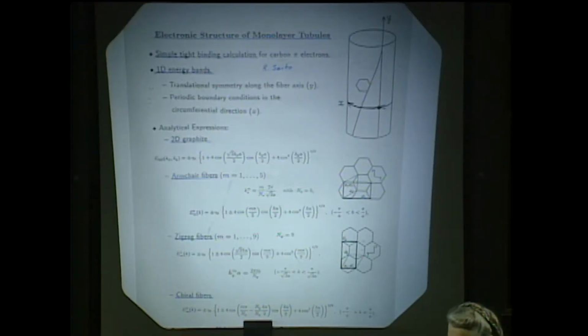The argument is based on the following concept, that when we have the tube, we make the tube like this, and we have a finite number of carbon atoms that go around the circumference. The number of wave vectors that we would have assigned to the system in reciprocal space, for those people that understand those things, is equal to the number of atoms. And as we go around the cylinder, we want our electronic wave function to be continuous as we go around. So going from this sheet to the next sheet, we should have continuity. So we match the boundary conditions, and that imposes certain restrictions on what the dispersion relations can be. What it all boils down to in the end is, and I guess that I need my next picture to show that.